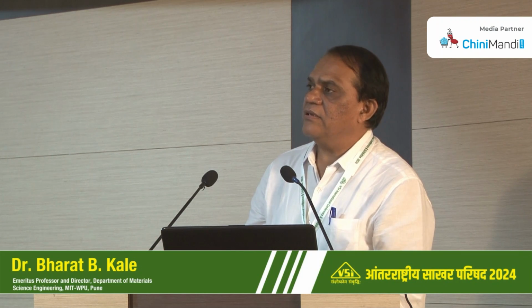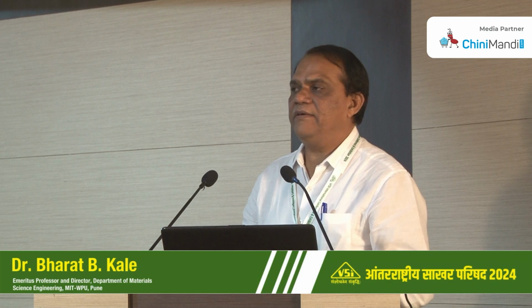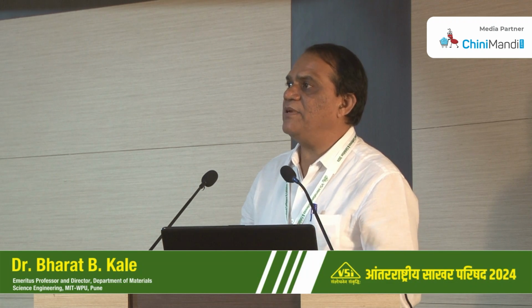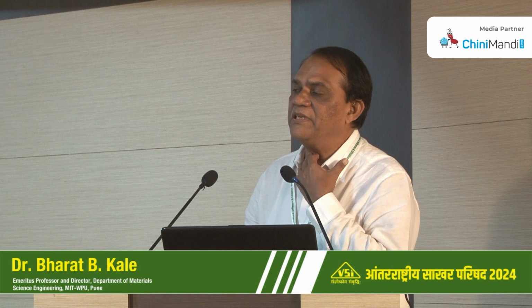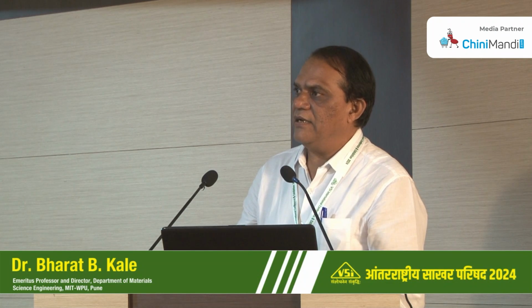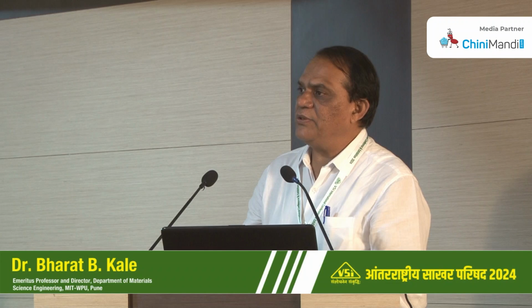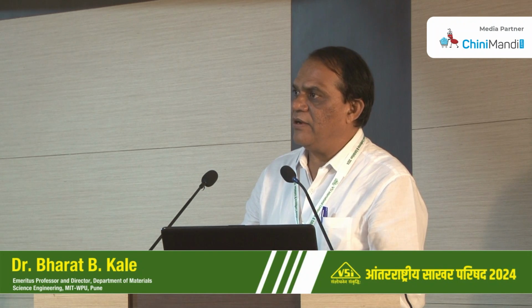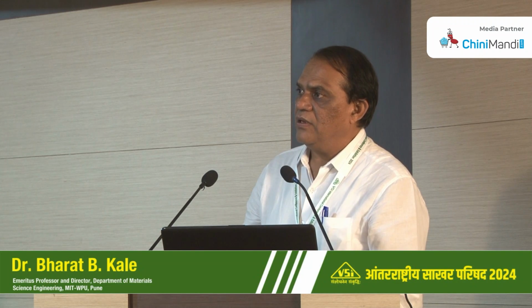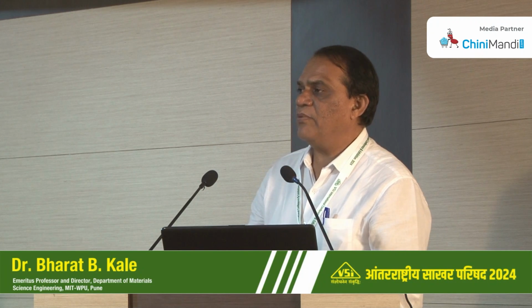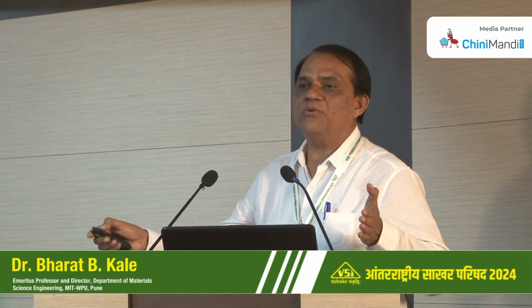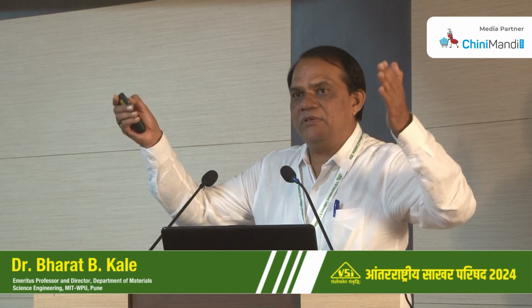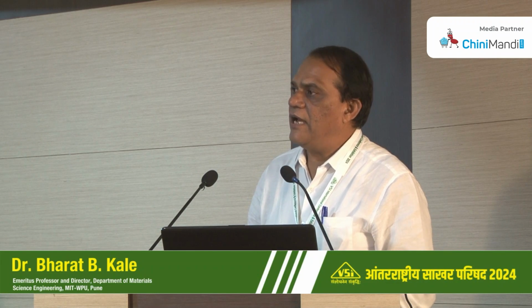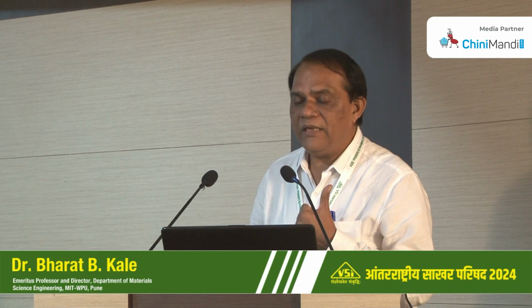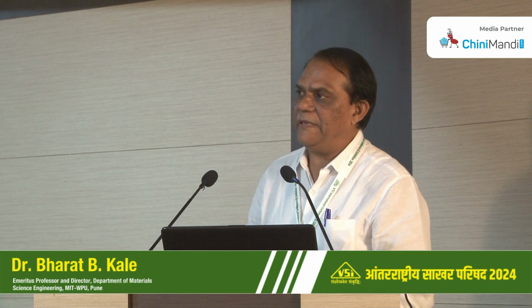And then we wanted to have bismuth sulfide in the glass, but we could not get bismuth sulfide, but we got bismuth particles in the glass. And here the advantage we got is that the band gap has been enhanced to almost 1.7 to 1.8 electron volts, which covers UV light to almost the IR region, so that we get a good spectrum of visible light. And we observe that this kind of glass may give very good photocatalytic activity.